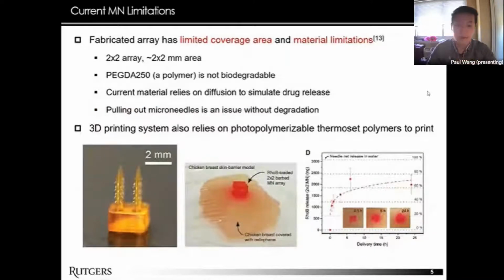However, the fabricated microneedle array has limited practical uses because of its limited coverage area and material limitation. Currently, the size of the microneedle array is restricted to millimeter scales. As you can see in the image, our array only contains around 4 needles in a 2 by 2 millimeter area. This is because our printer's projection area is only 24.4 by 13.8 millimeters, which limits how large an array we can create. This is good enough for basic drug release tests, as you can see in the bottom right 2 images, but it's not sufficient for real-life use when you need a lot of needles to effectively distribute the drug.